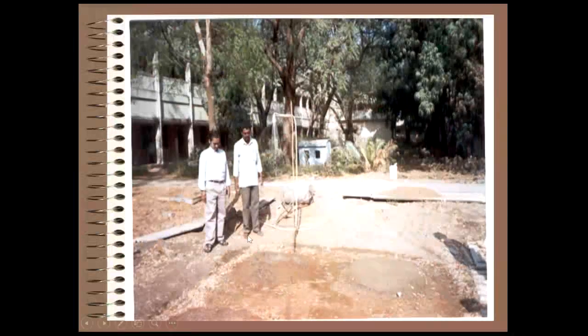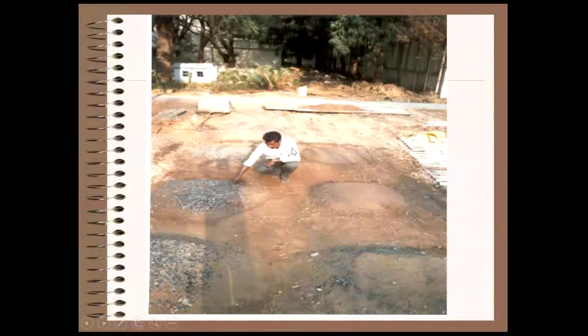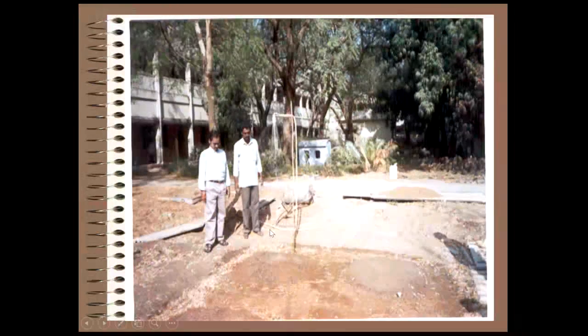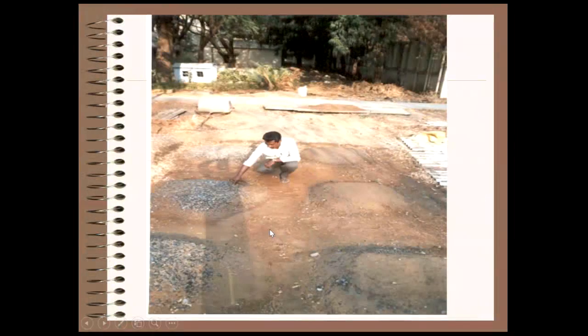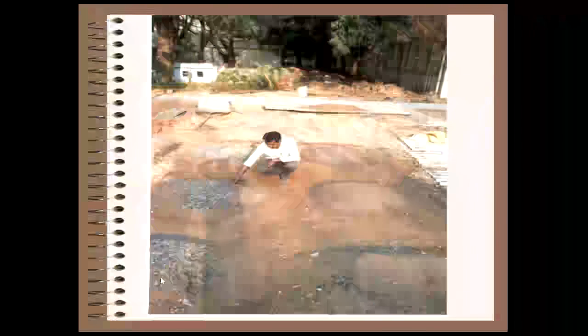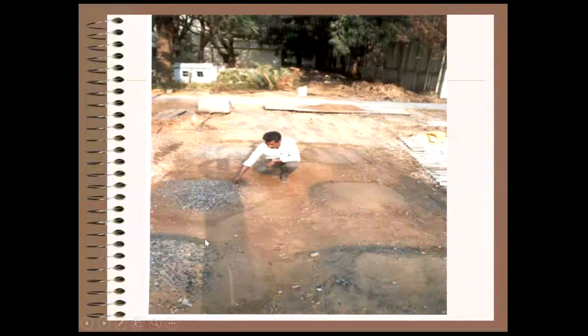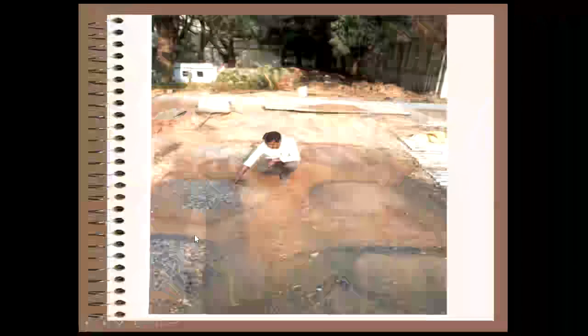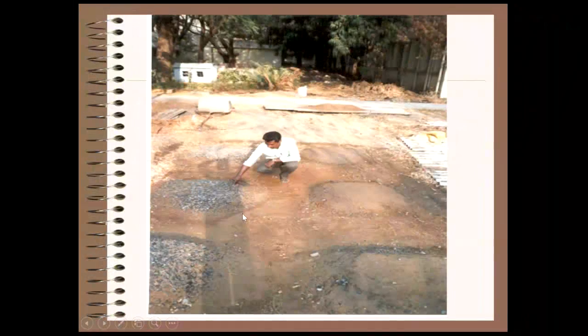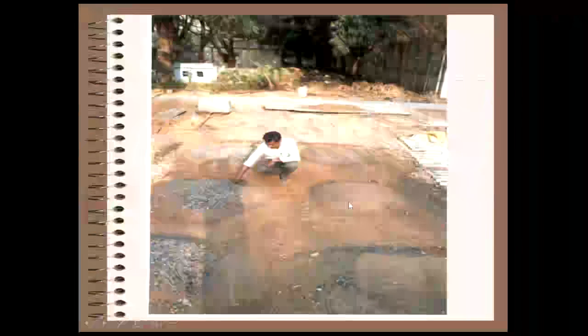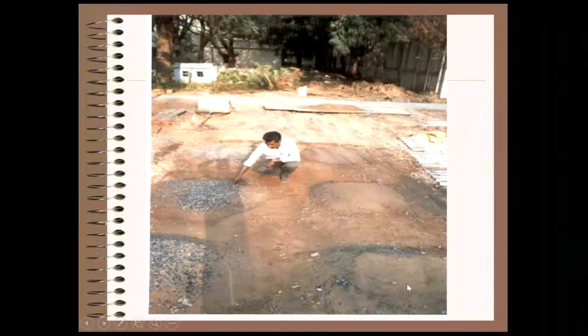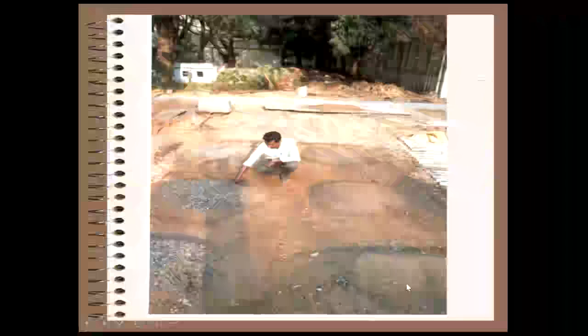Then also rain simulation we carried out using a shower. The shower we have used just to simulate the rainfall. Within 10 minutes, see how the aggregate is ravelled, all the material is washed out. This is what is a reality in the field. If at all unscientifically, without any blacktop, if we believe only earth roads will stand, this is how every monsoon our roads will be damaged. This 6% cement stabilized systems, they are intact, no loss.